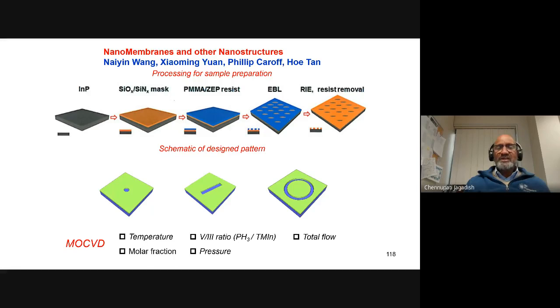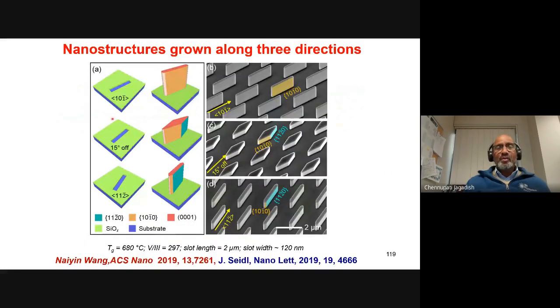And of course, Naiyin Wang has spent about 4 years optimizing a wide variety of growth conditions in order to be able to get good quality structures. So here is a case where Naiyin Wang opens the slot along a particular crystallographic orientation of 101 bar, and then puts it into an MOCVD reactor and heats it up to 680 degrees Celsius, introduces the gases needed for the growth of indium phosphide, and you can get these beautiful nanomembranes here, for example. But if you open the slot along another crystallographic orientation of 112 bar, you also get membranes, but these membranes are thicker, and they've got a different facet than this particular one here, for example.